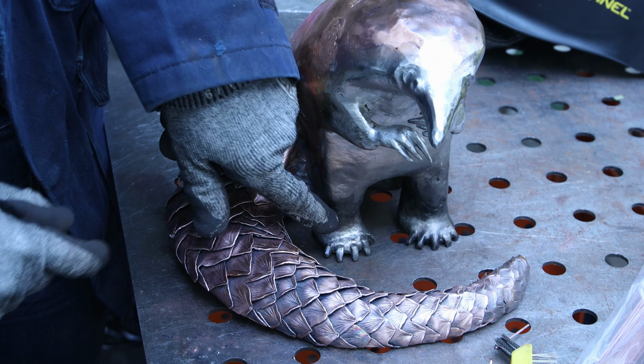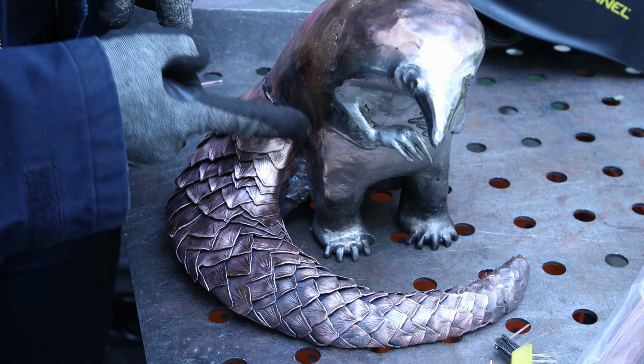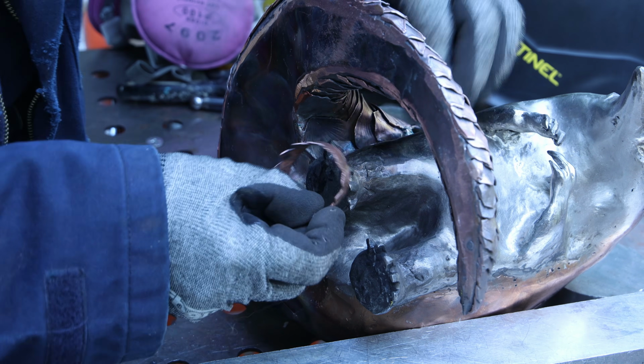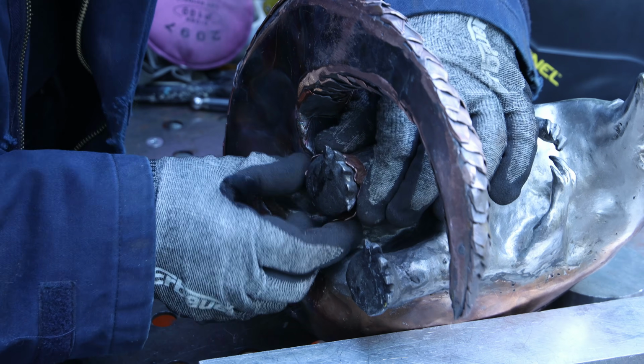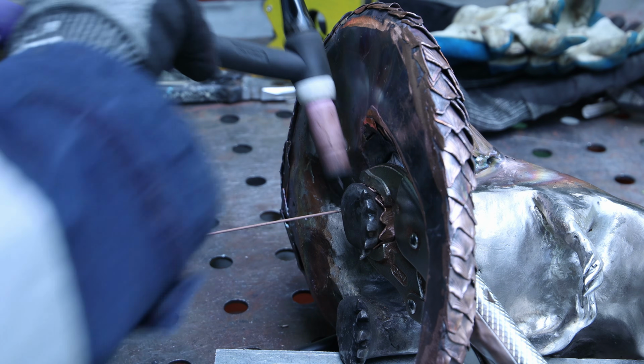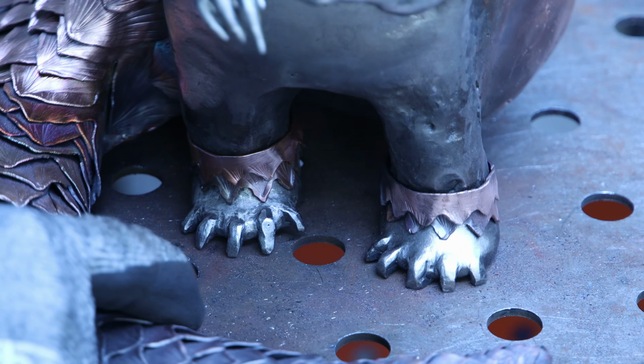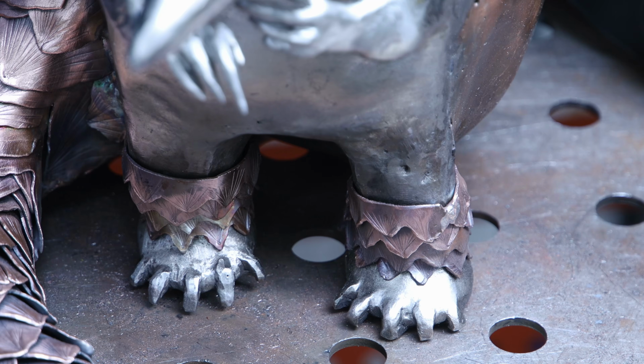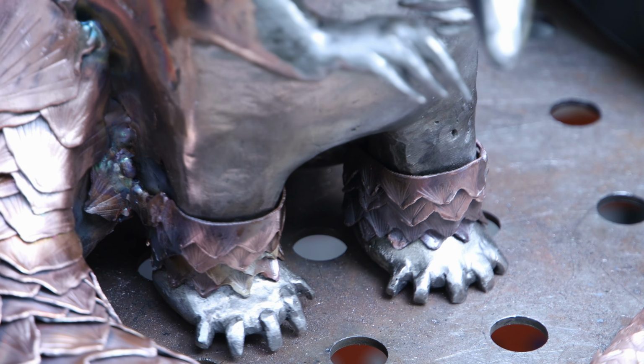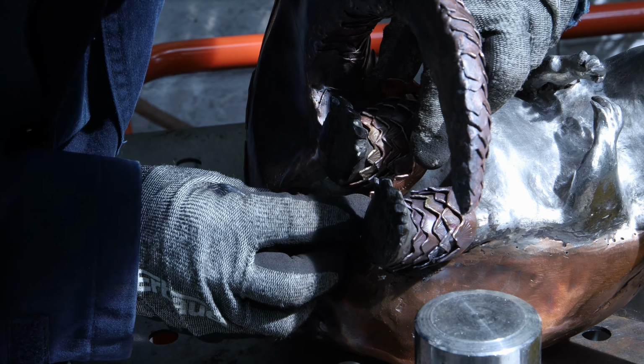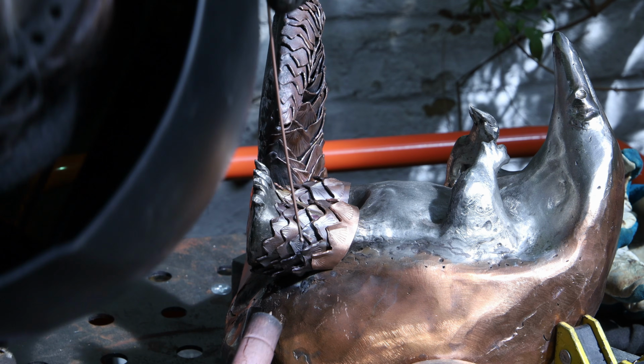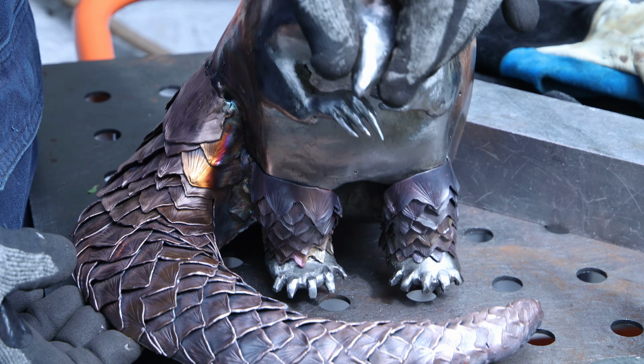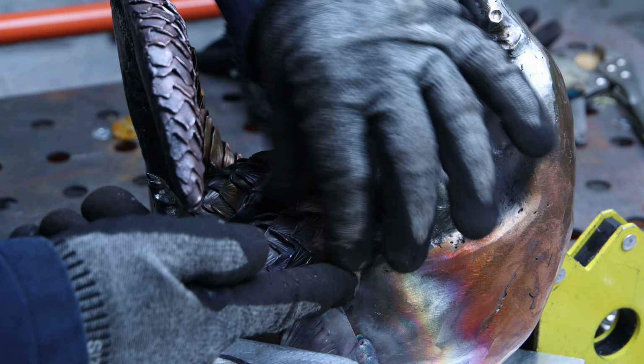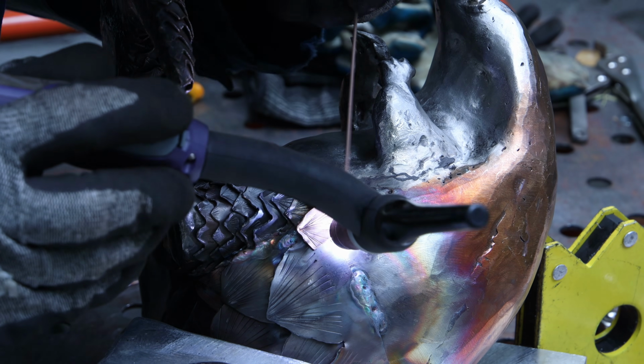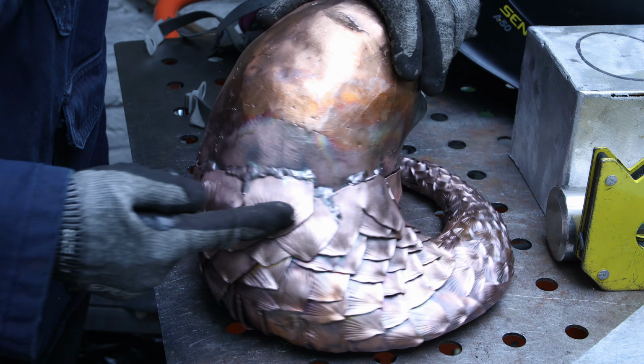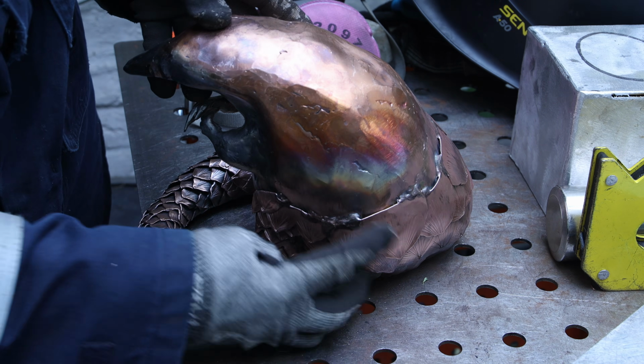Moving on to the back pose. I used the smallest scale available, created a little ring, then I pressed and held it against the pose, and I was doing the soldering at the back. I used 2 rows of the small scale, then went up and added 2 more rows of the next scale up, and I kept going until I built a little pyramid going upwards at a diagonal, I would say. I need those scales to blend into the much bigger scale of the rest of the body. So I went upward on the side, and then I also built up all the back. They will meet at the same height where the pyramid is finishing.